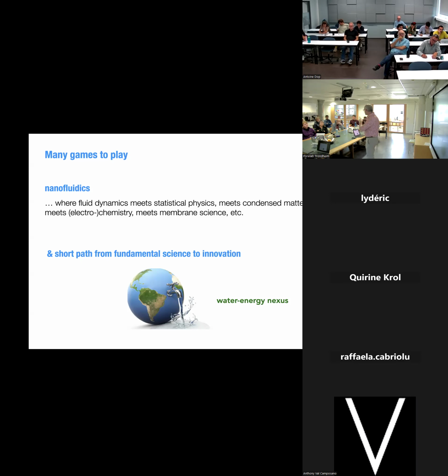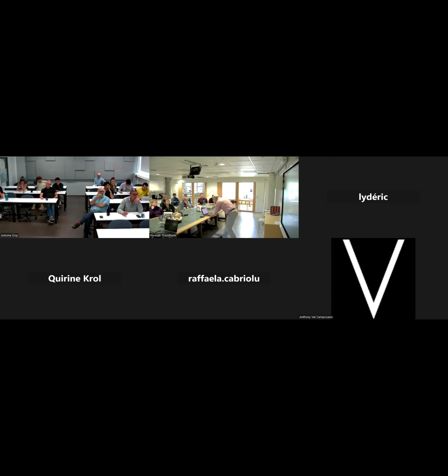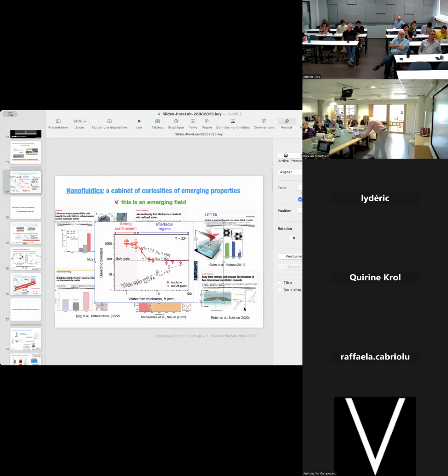Okay, this was the work of the group of André Geim and Fumagalli, so we didn't do this work. But actually, there are two aspects. Let me show it again. So these are the curves of Fumagalli in two papers. The first paper was this one, the bottom one, where the dielectric constant versus water film thickness goes down, and you see it saturates around 1 nanometer or so, at a limit of around 2, the optical limit.